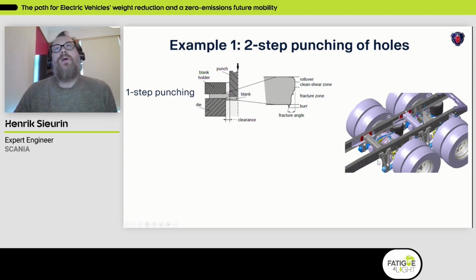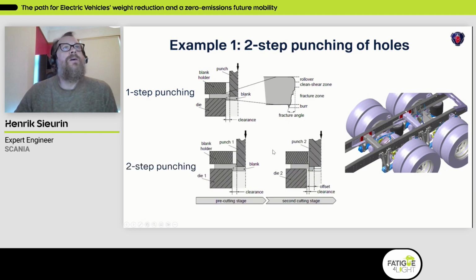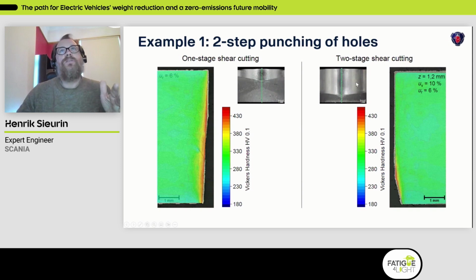So I have a few examples. Example one, two-step punching. In the side member, you have a huge amount of holes. And from these holes, fatigue cracks can initiate, especially if you have an empty hole close to a bracket, like you see in the picture. So when you punch a hole, you get a shearing zone and a fracture zone with a relatively bad surface roughness, and here fatigue cracks can initiate. But if you do the two-step punching, then you first punch a smaller hole with a smaller diameter, and then you come after with a slightly wider punch to shave off a piece around the edge. And by doing this, you get a much nicer surface.